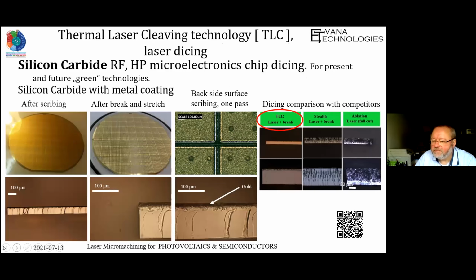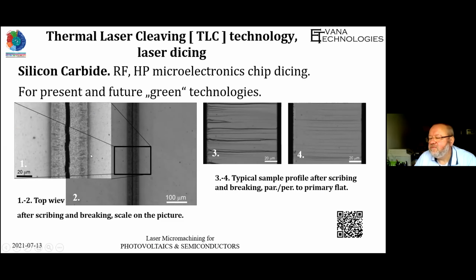We can see this is silicon carbide after scribing and after breaking. It means we can make dicing of this material very easy and really without big limits on the thickness of the material, because we tried up to 400 micrometer silicon carbide, and it was quite successful cleaving of the material without any loss of line along the cleaving street. You can see here the after-breaking view and cross section of the material for 100 micrometers, I think.